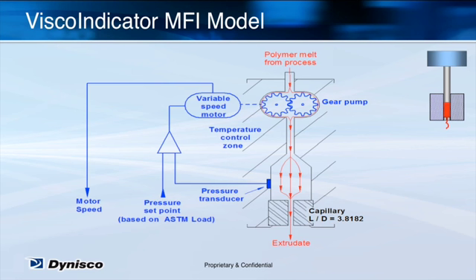In the ASTM mode of operation, the pressure defined by the load and piston specified in the ASTM method is recreated by controlling the gear pump flow rate using data from a pressure transducer. The material flow rate is calculated from the speed of the gear pump. Remember that a gear pump is essentially a positive displacement device that pumps the melt at a constant rate regardless of the resistance to flow.